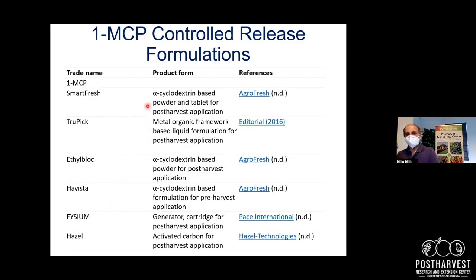If you look at it, most of these formulations are using alpha cyclodextrin, which is a molecular trapper. If you want to think about it, it traps the 1-MCP, and based on the humidity of the environment, it releases the 1-MCP there. The other that has emerged is the metal organic framework. These are very good absorbers of gases, very sensitive to humidity, and can provide controlled release over an extended period of time for post-harvest applications. Then something that has emerged recently is activated carbon, where the activated carbon is used to absorb 1-MCP, and this sachet of activated carbon, which is more benign than metal organic framework, could be used as a material to provide the release in this environment.